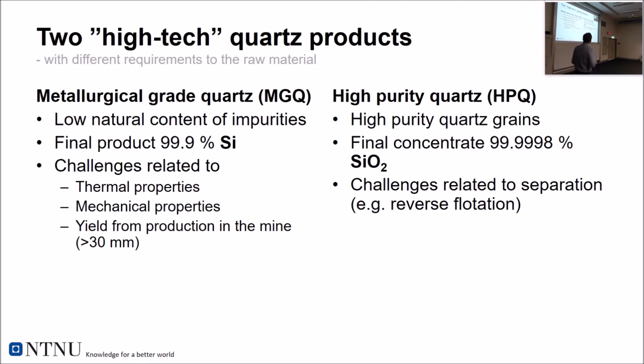And in the silicon furnace, thermal properties of the quartz, thermal strength or thermal resistance of the quartz is very important. The concentrate that's fed to this furnace is 30 to 100 millimeter size. So everything less than 30 millimeters is regarded fines. In some cases, they may add some controlled amount of 20 to 30 millimeter quartz as well. But mainly it's from 30 to 100 millimeters. And the yield from the mine is defined by how much of the quartz is produced as